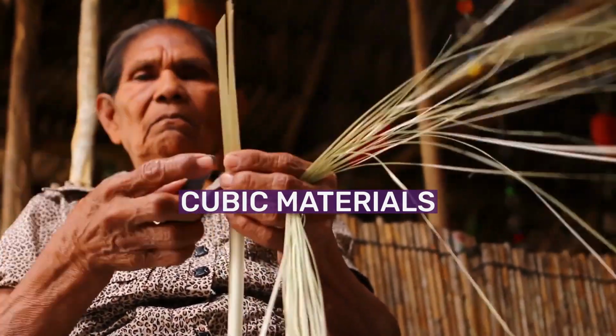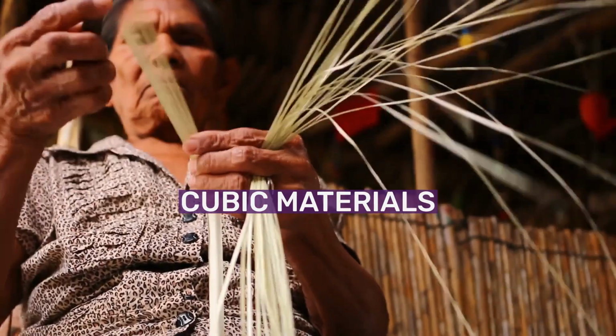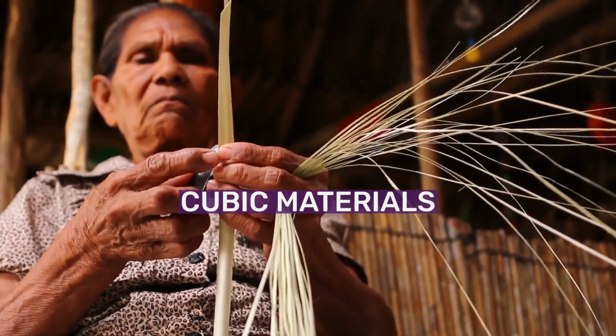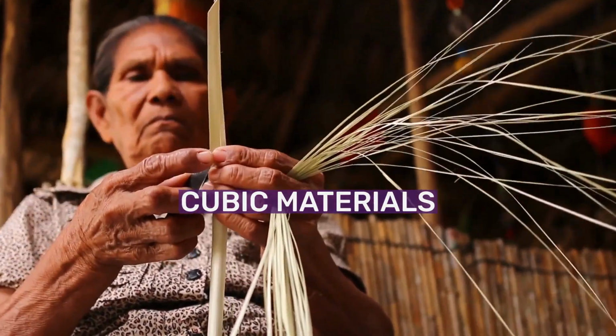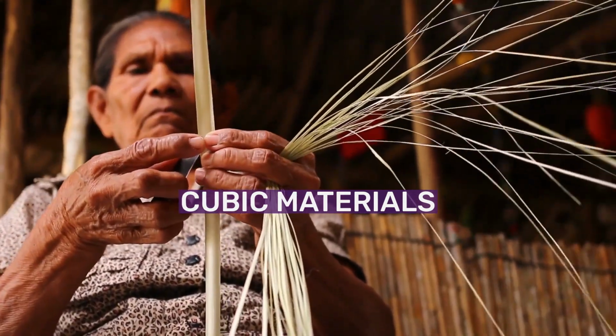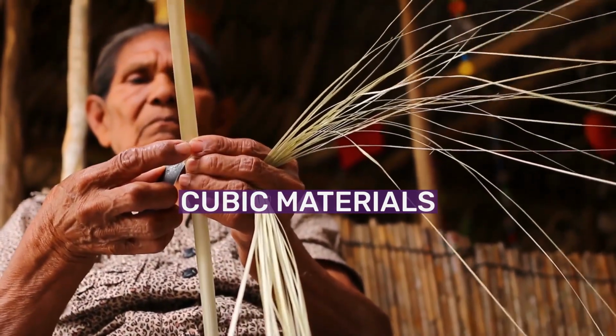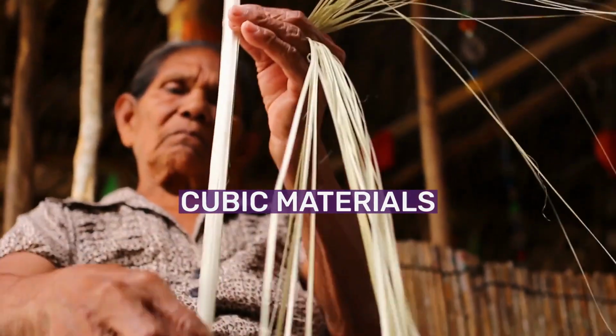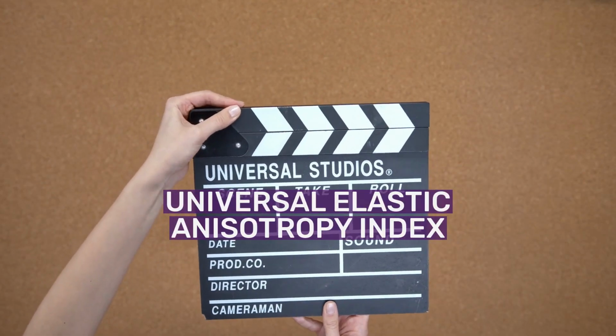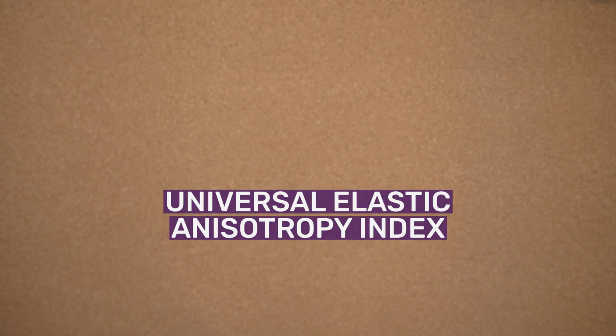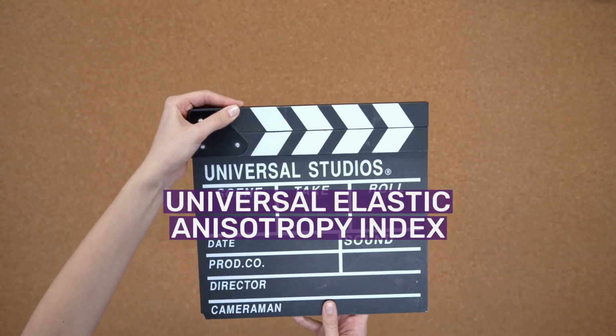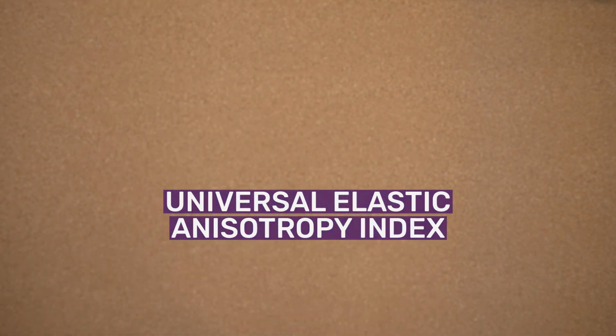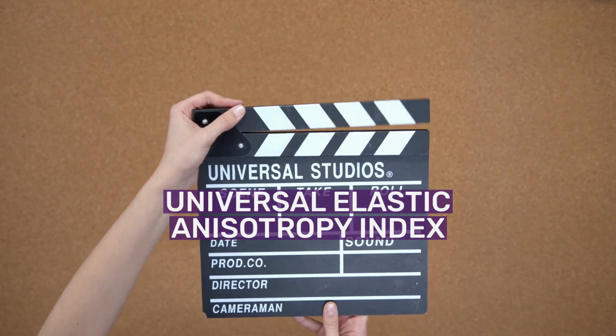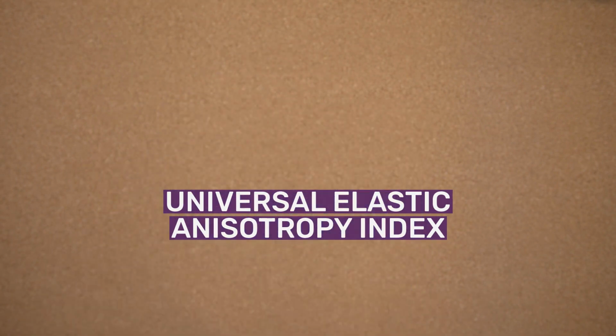Therefore, we can think of the ratio as the relation between the shear modulus for the cubic material and its isotropic equivalent. $R = \frac{G}{E/(2(1+\nu))} = \frac{2C_{44}}{C_{11} - C_{12}}$. Universal elastic anisotropy index. The Zener ratio is only applicable to cubic crystals. To overcome this limitation, a universal elastic anisotropy index was formulated from variational principles of elasticity in tensor algebra. It is now used to quantify the anisotropy of elastic crystals of all classes.